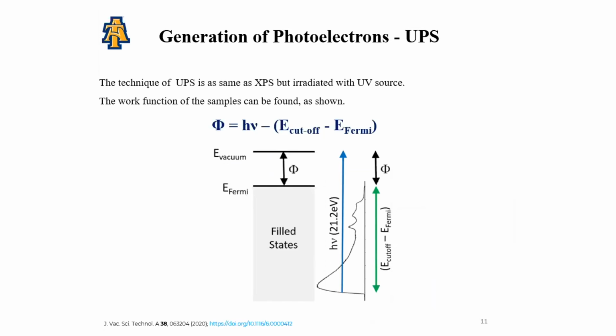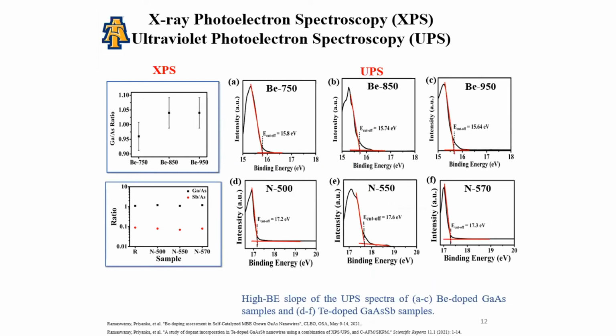XPS and UPS measurements were performed with a Thermo ESCALAB 250Xi using a monochromated aluminum K-alpha X-ray source and helium-I photon source, respectively. The atomic ratios of gallium over arsenic for beryllium-doped gallium arsenide and tellurium-doped gallium arsenide antimonide samples are found to be around 1, while antimony over arsenic for tellurium-doped gallium arsenide antimonide samples is found to be around 0.07.